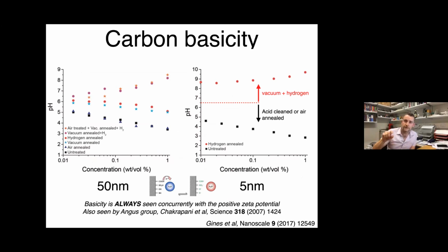You put them in water, COOH becomes deprotonated. So there's a negative charge on the particle, and the solution must go negative. That's what you see as a function of concentration: the more particles you put in, the more acidic the solution goes, right? So what happens in the positive case? Well, you see carbon basicity, right? So this is also very interesting because it means that you're making the sample go positive, but at the same time, you're taking protons out of the solution, right? That's basically what it means.